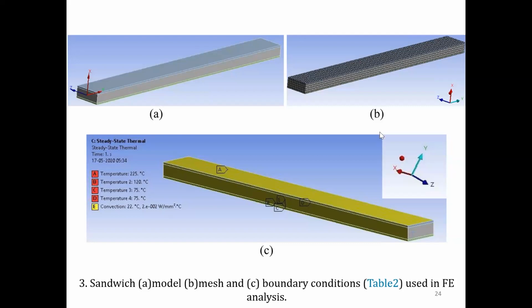And while printing, we kept the layer thickness of each layer, because we all know that in 3D printing, we deposit layer by layer. So we kept the layer thickness constant as 500 microns. So in total, there are 16 layers. The same has been also modeled in 3D printing. So before meshing, sandwich elements like skin, core, and skin are coupled for effective heat transfer.